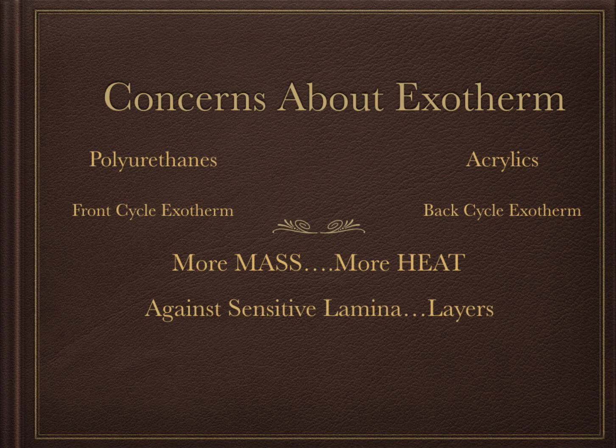And so the golden rule is if you're up against something sensitive or you're not sure, you go in layers. And generally 2 layers is enough. Once you lay down an initial layer and that cools, then you can bulk on top of it without transferring heat to the foot because the first layer acts as a heat barrier.